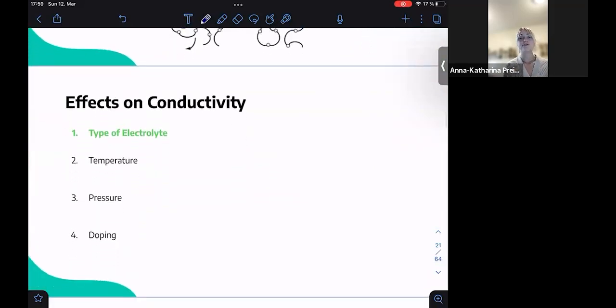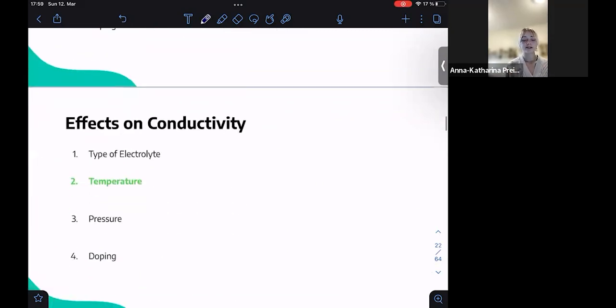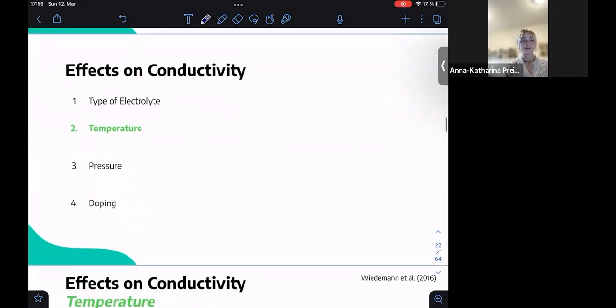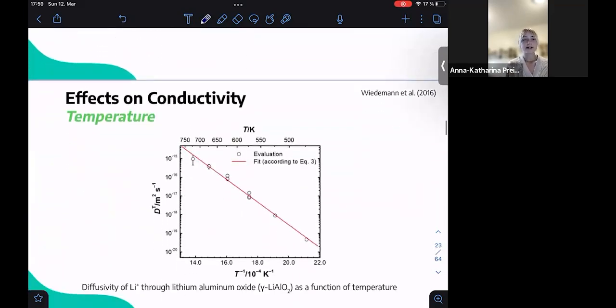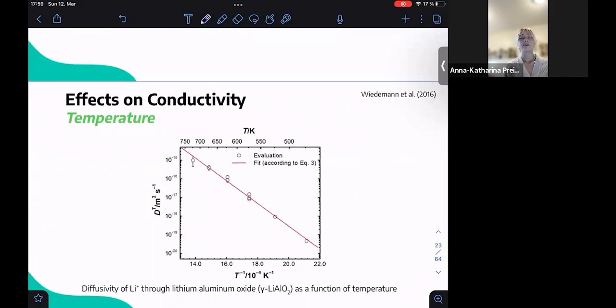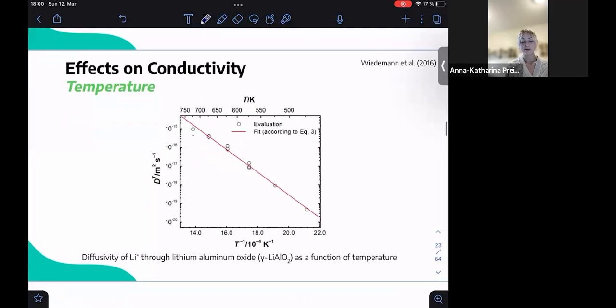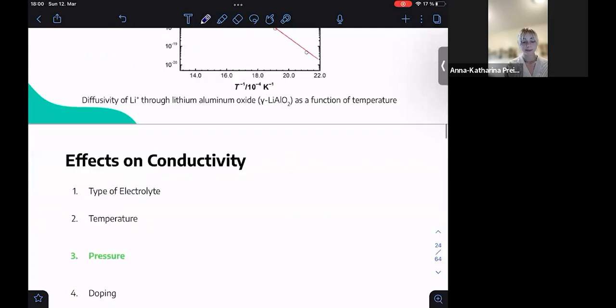So we looked at how the different types of electrolyte affect the ionic diffusion through the solid electrolyte, but there are also other factors which will influence it, such as temperature. The ionic conductivity of solid-state battery electrolytes typically increases with temperature due to greater mobility of ions at higher temperatures. However, at excessive temperatures, it can also cause thermal instability and reduce the lifetime of the electrolyte. Here we can see in this diagram a pretty linear relationship between increasing temperature and more mobility.